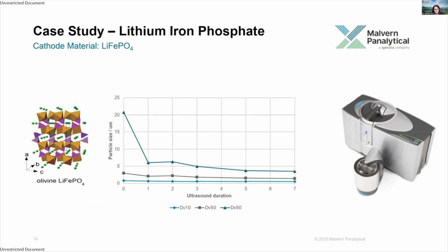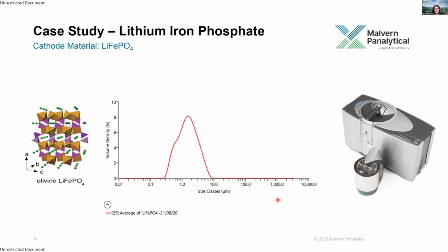For this lithium iron phosphate material, which we've also measured in water with a surfactant, we can see that we definitely need ultrasound to disperse this material. So at the beginning, before the application of ultrasound, we have quite a large material, and that's highly agglomerated, and this takes several minutes of ultrasound to disperse before we get to the end where we have a fairly stable percentiles. So the final distribution that we end up with for this material is smaller than the previous example, and we can see that it clearly has a broader size distribution. So this is going to impact the exposed surface areas and the packing density of the material, and likely give us higher specific powers.